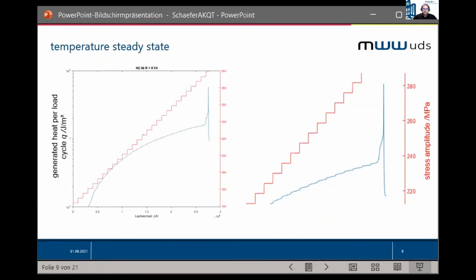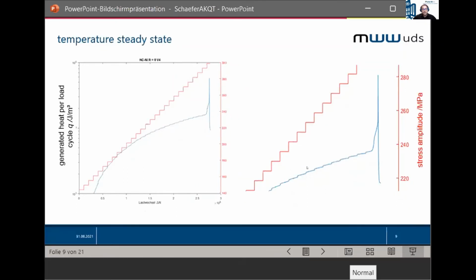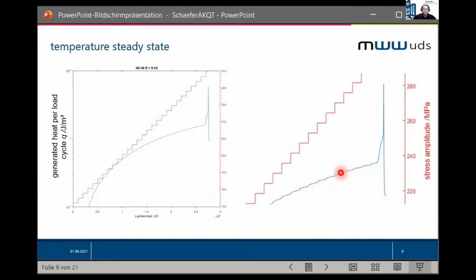So, if we make this load increase test, we must ensure that we get a steady state of the temperature, as you can see here. To achieve a steady state of the temperature, or the heat generated per load cycle, is the blue curve. To get the steady state, we had to wait a couple of load cycles. In this study, it was not enough load cycles, so we have to increase the number of load cycles and the test becomes longer, but it is necessary to achieve the steady state for the further evaluation.